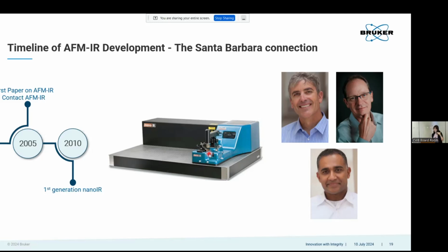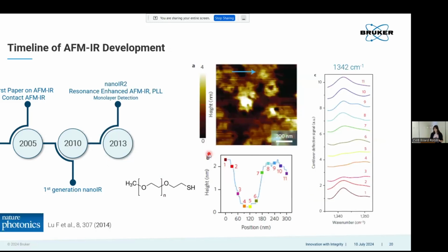It's also, at this point, only sensitive to materials which are upwards of 50 nanometers thick, which seems pretty thin, I think, in most contexts, but in the context of nanoscience, is really immense. And so you're looking at materials that have to be smaller than 1 micron, but larger than 50 nanometers. You're really restricted in the type of material that you can use to look at it.